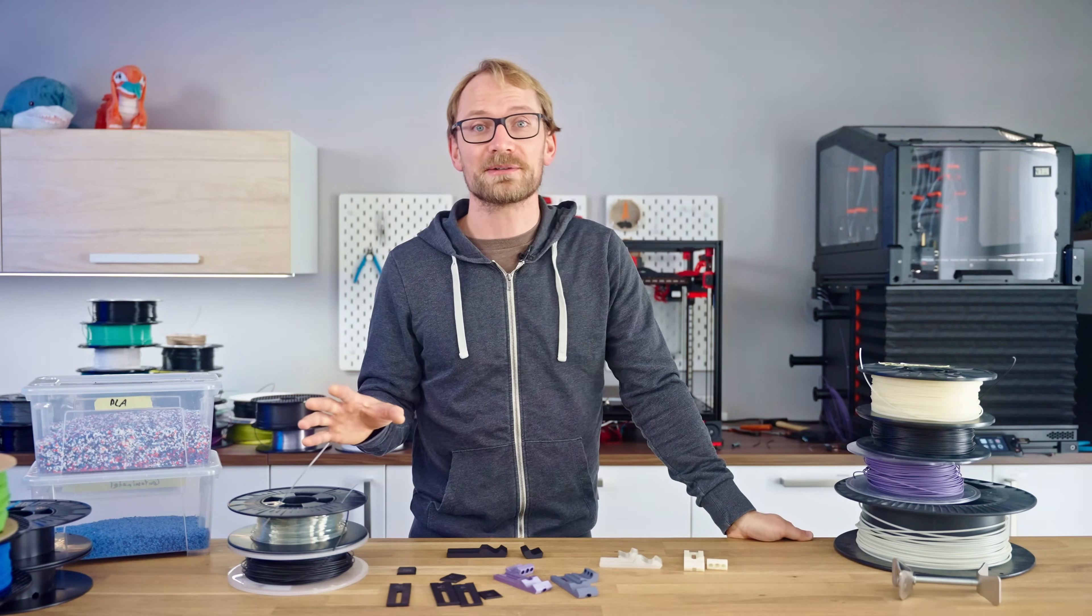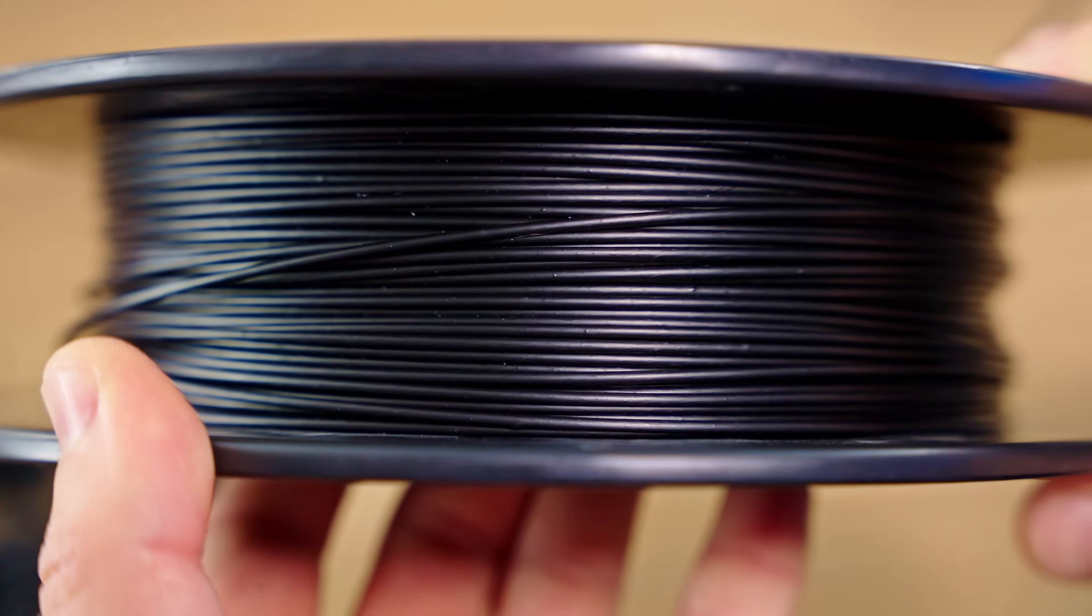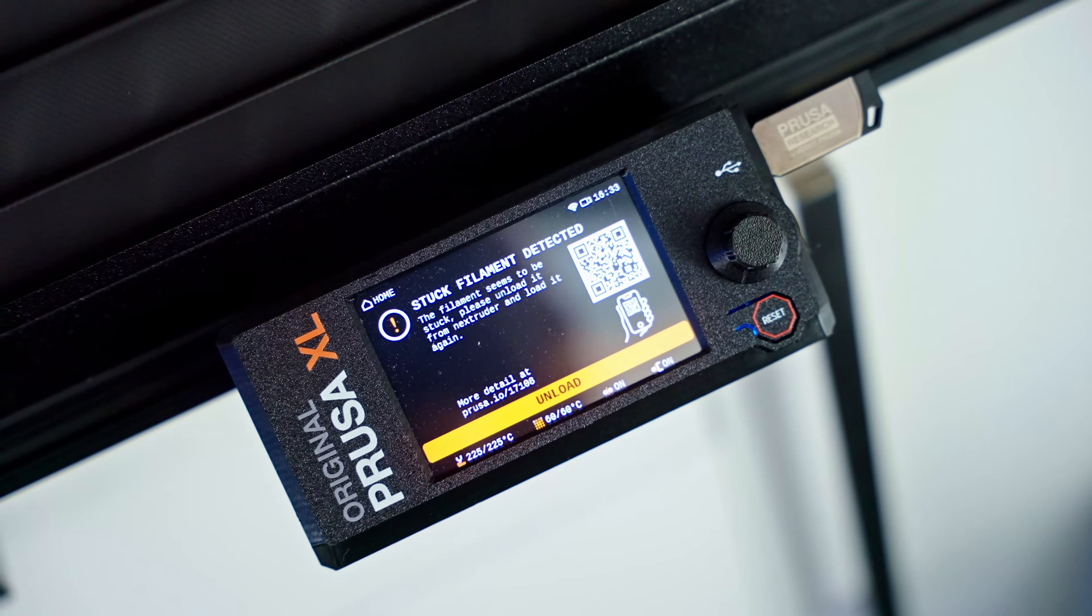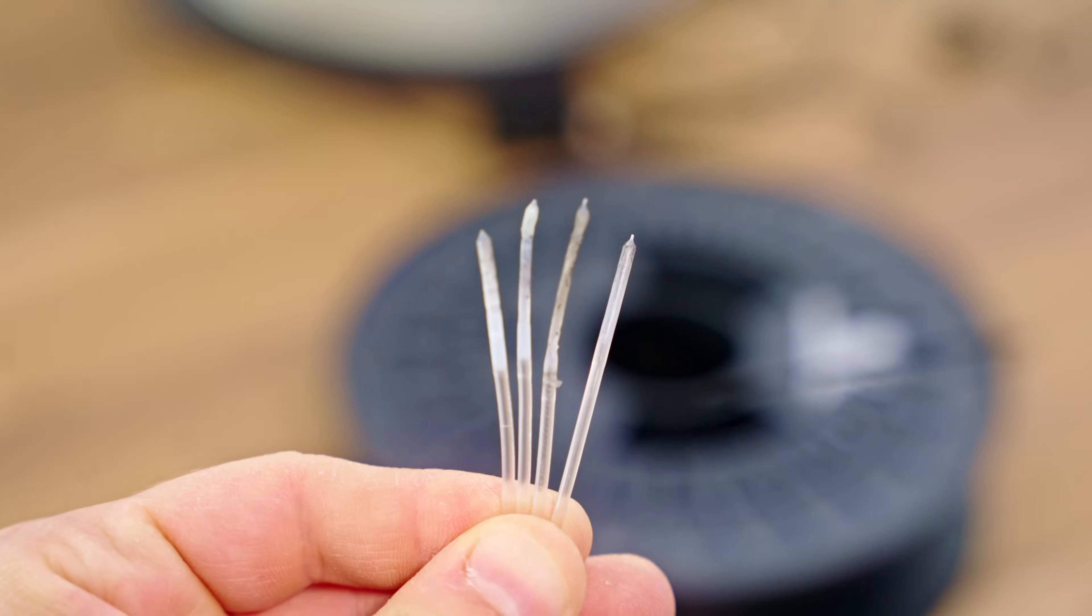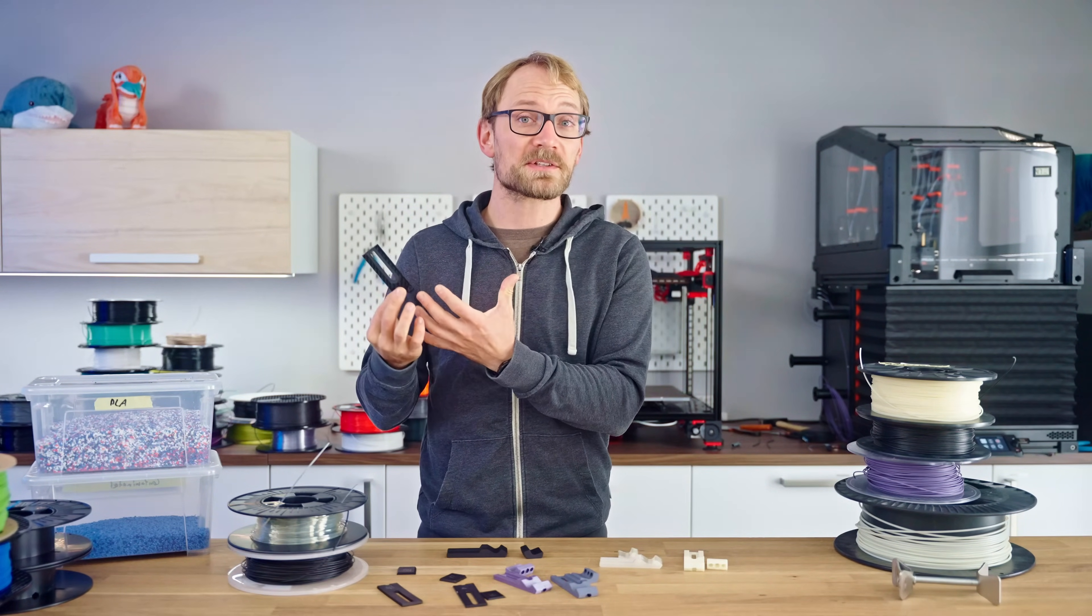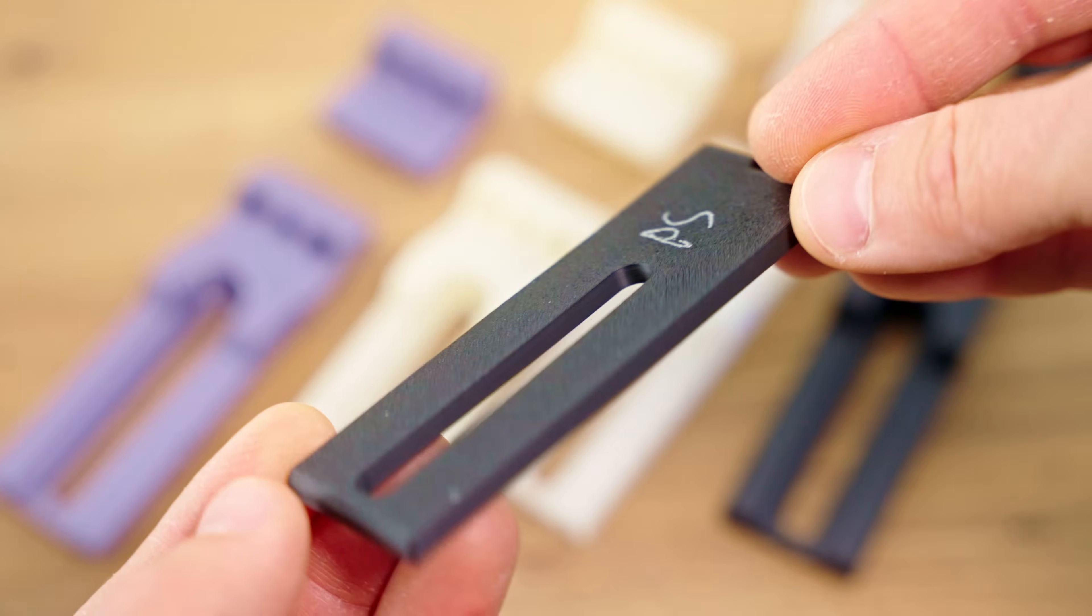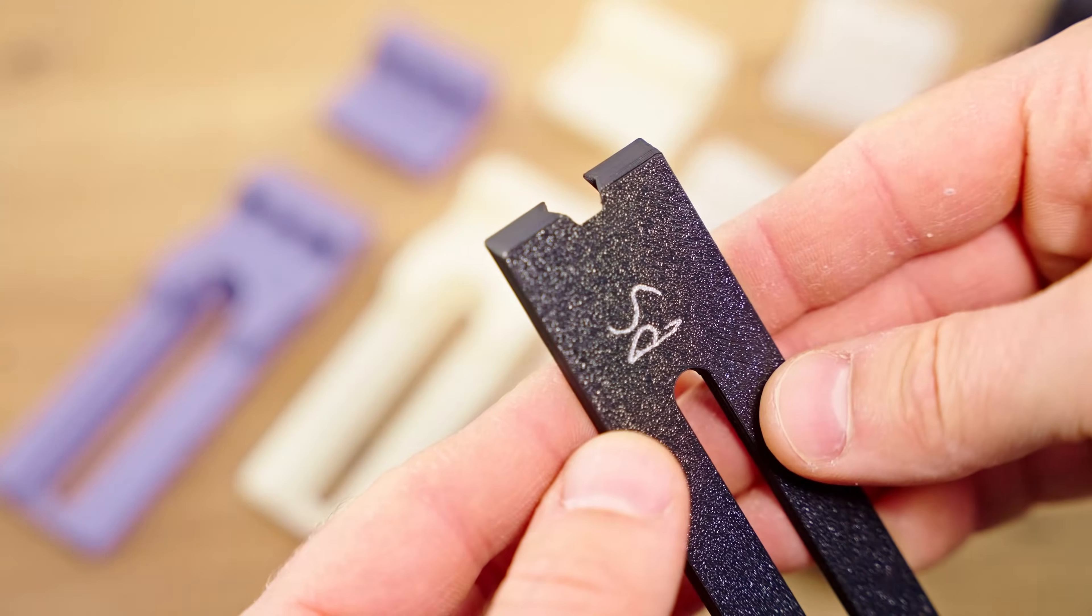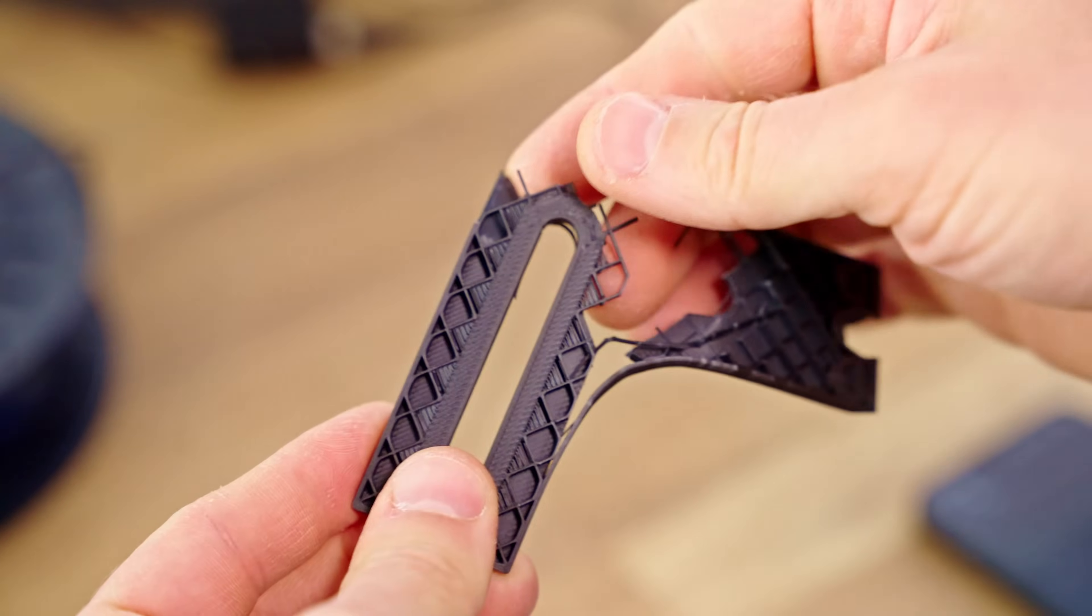One thing that I realized after the fact with all of the materials is that I should have dried them more. So occasionally, I got these little steam pockets in the filament that would be too big to fit through the extruder, and the XL would send me a notification and be like, little help here please. But on top of that, I think the polystyrene spool material didn't clean off the labels well enough, and that ended up creating an unmeltable residue that would clog the nozzle. The thing is, more aggressive solvents that would clean off the labels are hard to use with that styrene material, because they also start dissolving the spool itself, so you end up mixing it all together. But even for the bit that it did print, the material looks brittle and dry, for lack of a better word. It might just be that these spools were already made from a recycled, low-grade material, because honestly, for a spool, it just really doesn't matter all that much.